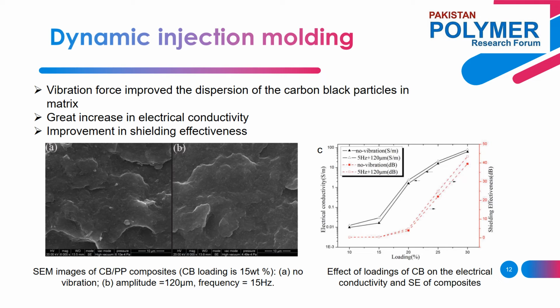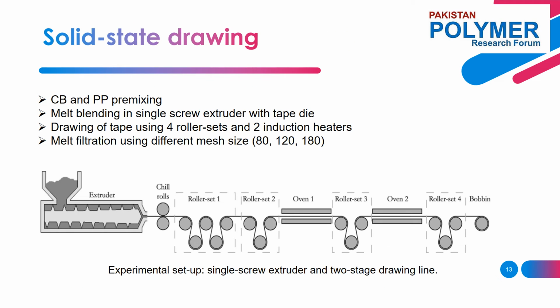After applying vibration force to the injection molding process, the rising trend of electrical conductivity is similar to the result with no vibration. Compared with no vibration, the electrical conductivity shows a great increase when the content of carbon black is more than 20 weight percent, because of the introduction of the vibration force field. Overall, research on the properties of PP and composite products by dynamic injection molding showed that the introduction of a vibration force field could effectively improve the dispersion of filler and the differences of electrical conductive distribution in different parts of the composites. Next is solid state drawing of post-consumer isotactic polypropylene.